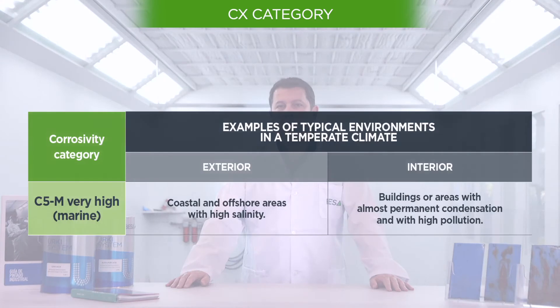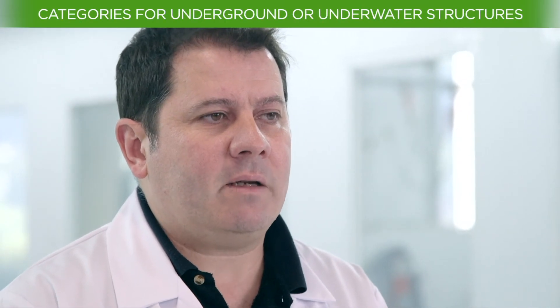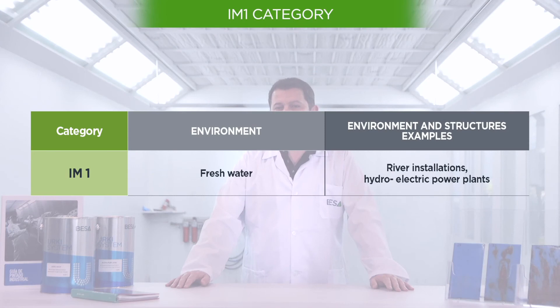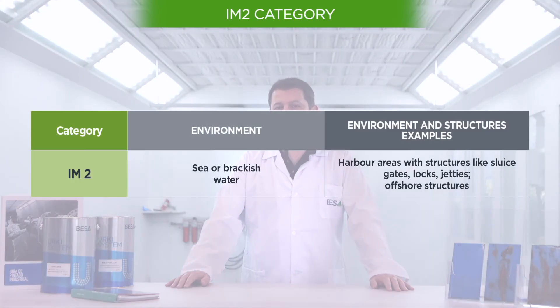CX is applicable to areas at sea, industrial areas with extreme humidity, aggressive or tropical atmospheres. For structures submerged in water, the standard establishes four categories: IM1 for fresh water such as river installations; IM2 for sea or brackish water such as underwater structures without cathodic protection; IM3 for soils such as underground tanks or steel pipes; and IM4 for sea or brackish water such as underwater structures with cathodic protection.